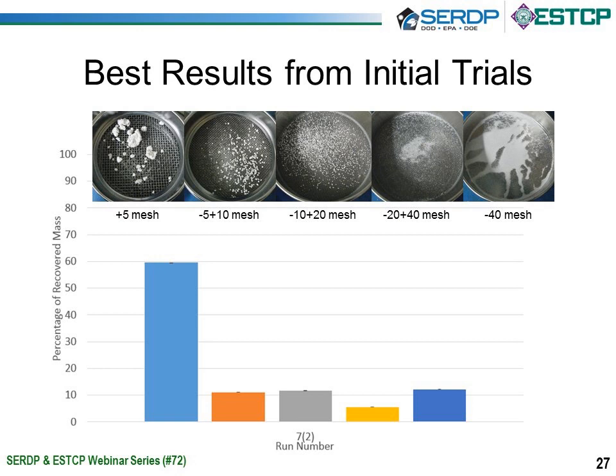This slide shows our sieve cuts of the material. As you can see, we had significant large granular formation on the very left-hand side sieve there. You can see that the majority, approximately 60% of our recovered mass was in the 5-mesh sieve. We had very little material in our optimal sieves, which is the 10 and 20 mesh. And as you can see on the far right side there, we had quite a bit of pulverized material that turned into very, very fine material that was collected in the pan.